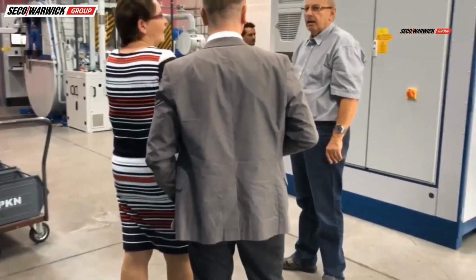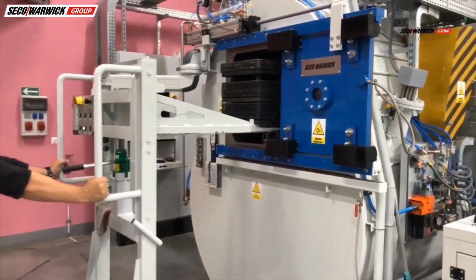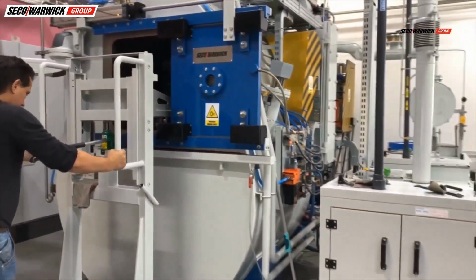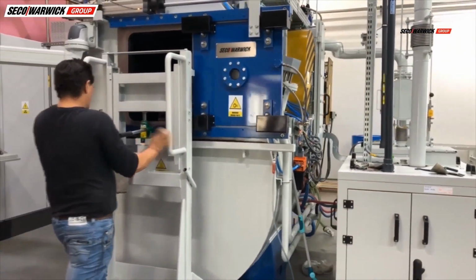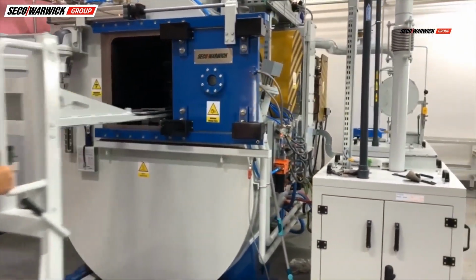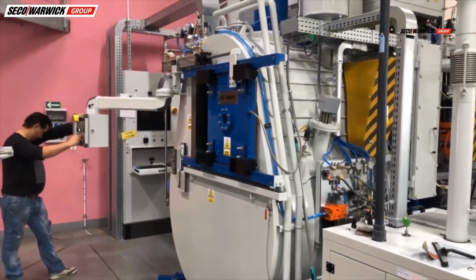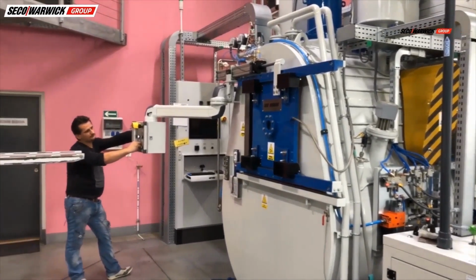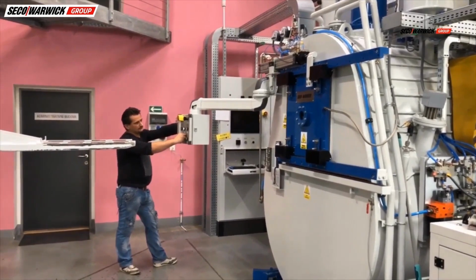Low pressure carburizing plus oil quenching means that oil quenching allows to heat treat low-grade steels by low pressure carburizing, and it makes this technology the most universal of all. However, you still have to deal with oil residues.